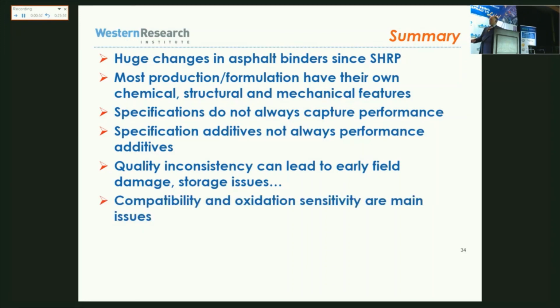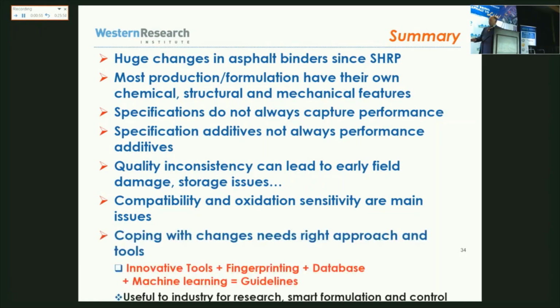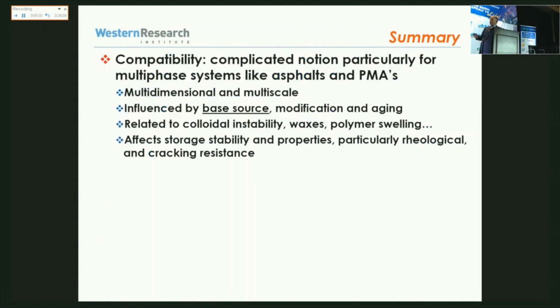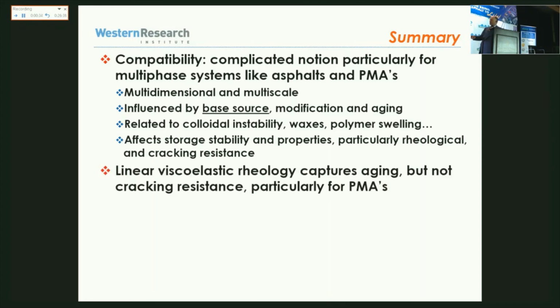Compatibility and oxidation sensitivity are the main issues. We can cope with that with the right approach, with the right tools, and that can be useful for the industry to formulate binders. So let's focus a little bit on the compatibility. It's a very complicated notion, particularly in the case of polymer-modified asphalt. It's multi-dimensional, it's multi-scale, it's influenced by a lot of factors, including the base asphalt, the process, and everything. It's related to colloidal instability, but not only. It's also related to waxes, to polymer swelling, and the change in colloidal instability because of polymer. It affects storage stability and the properties, and particularly the cracking resistance.